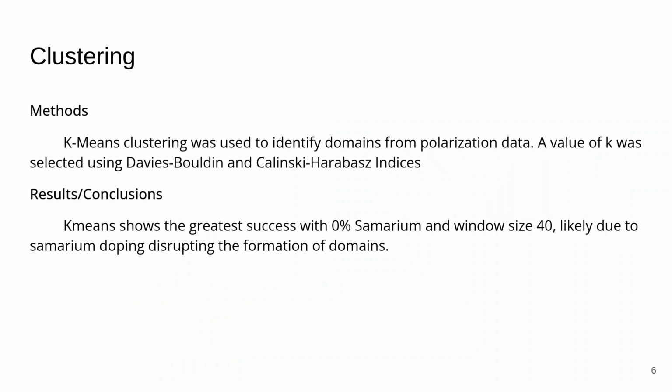We also performed clustering on the data. We used k-means, and we independently selected values of k, or number of clusters, using the Davies-Bouldin and Calinski-Harabasz scores. What we found is that k-means shows the best success with 0% samarium doping and window size of 40.